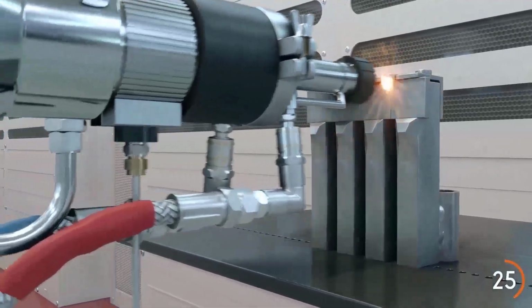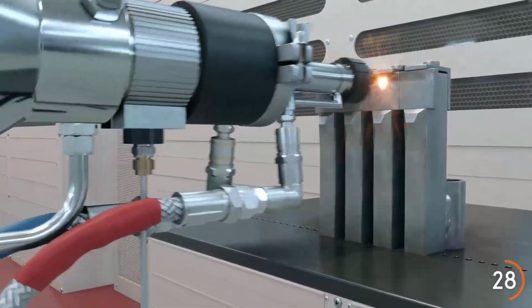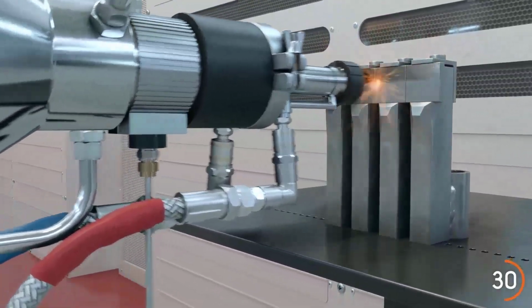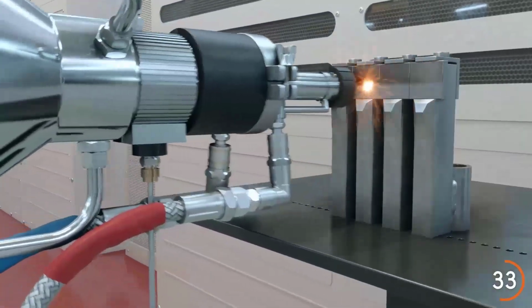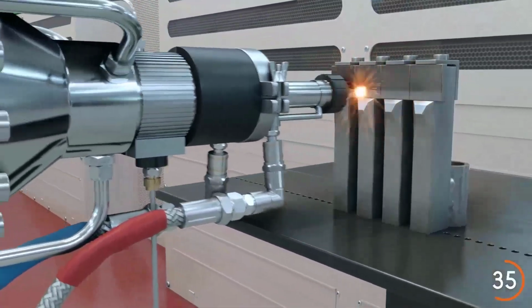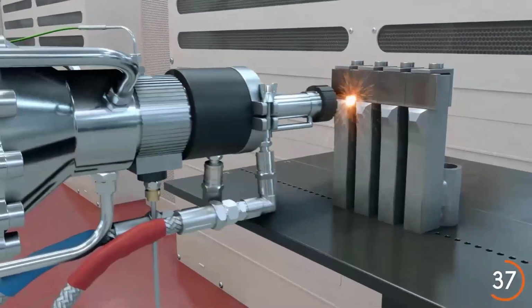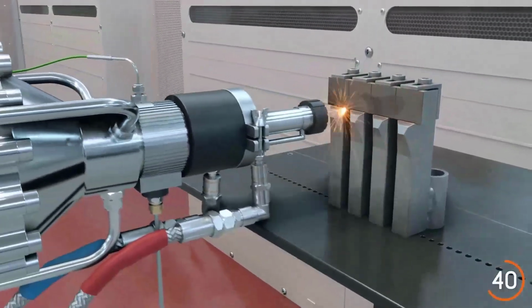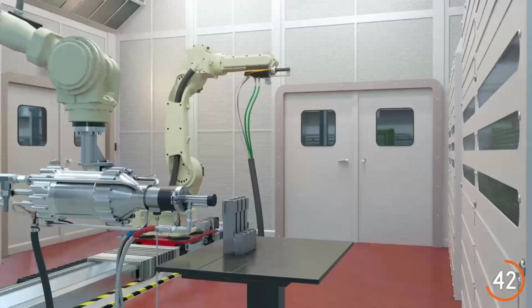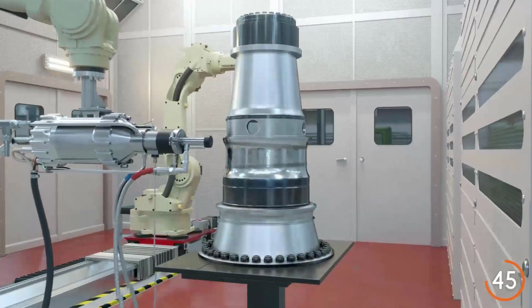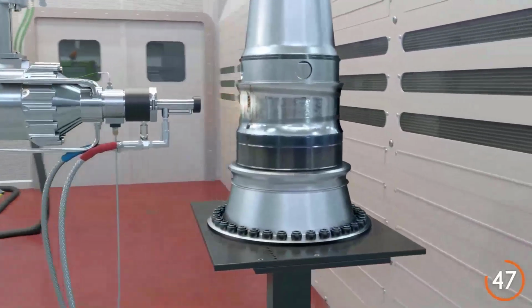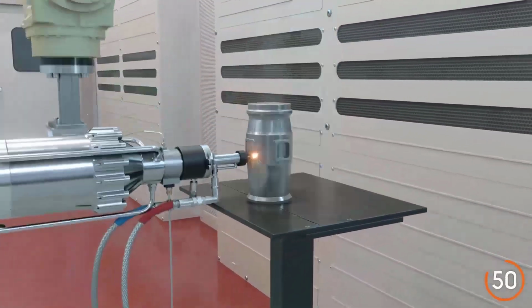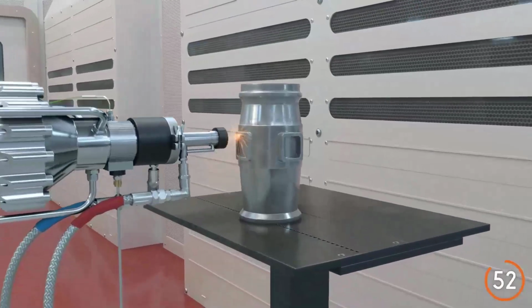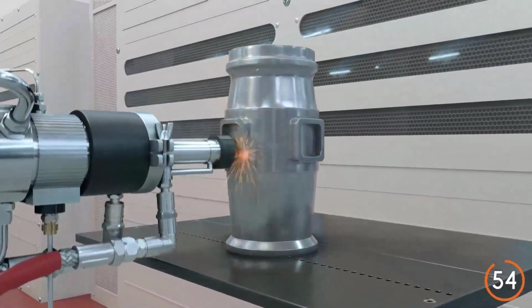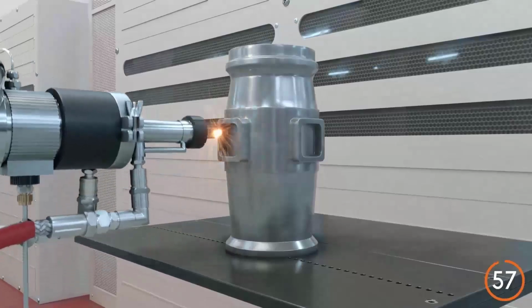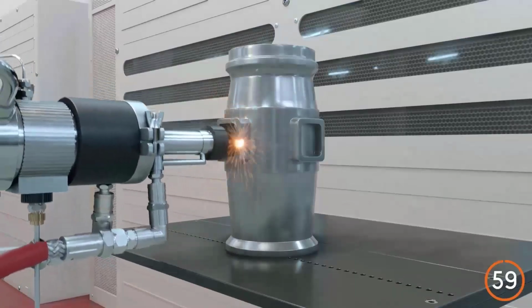The solid-state nature of the process brings a number of benefits, including the ability to deposit oxygen-sensitive materials without shielding, such as aluminium and titanium, and create deposits with high density and bond strength, with manageable levels of residual stress or distortion. The process is well suited to repair applications and is qualified for use on a number of aerospace and defense platforms. There's also an increasing interest in additive manufacturing due to the very high deposition rates available, the ability to process challenging materials, and the potential for multi-material structures.